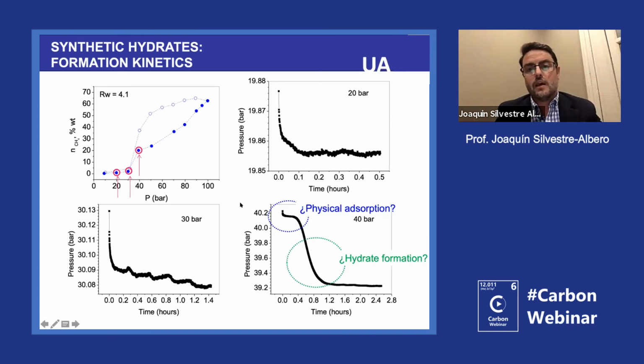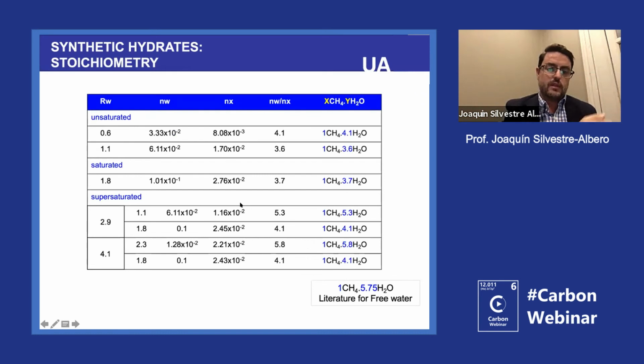As we knew how much methane we are absorbing in the isotherm, and we also knew how much water we had in the system, we were estimating the ratio of methane to water in the final point of the isotherm. And we were doing this for different saturations of the carbon, from the undersaturated carbon to the supersaturated, oversaturated. And it's nice because you can see that the stoichiometry is always very similar to the stoichiometry of the methane hydrate in the natural environment.